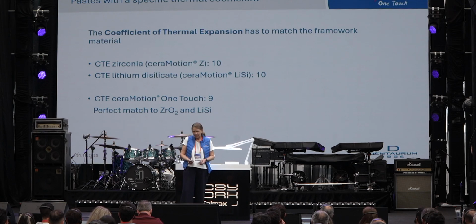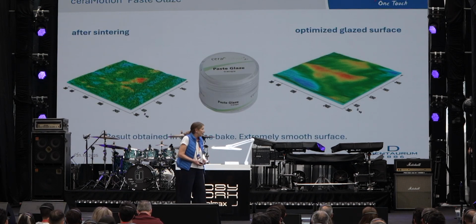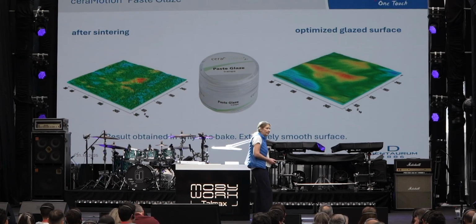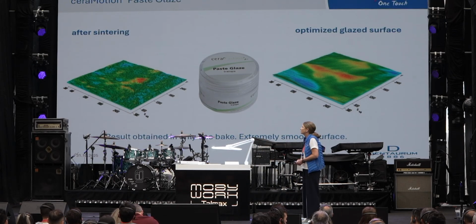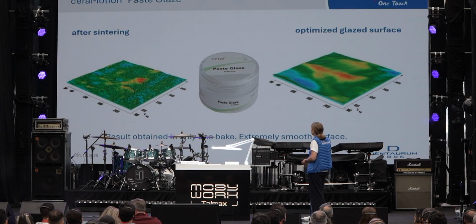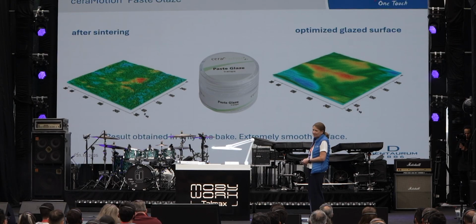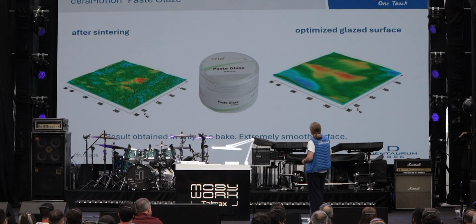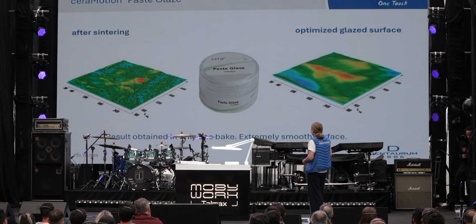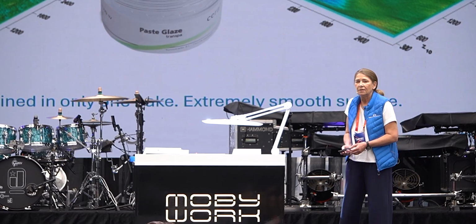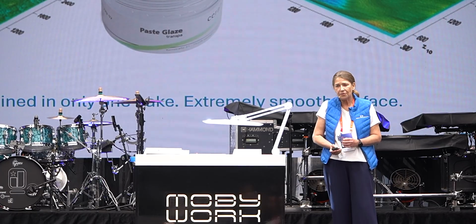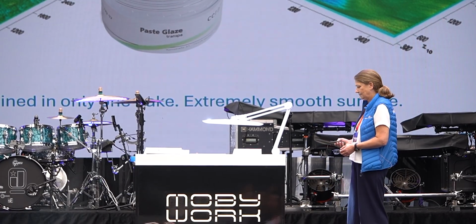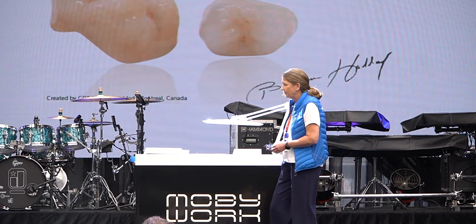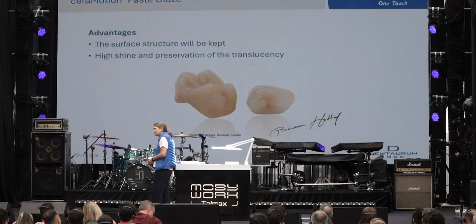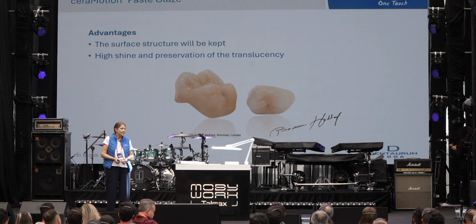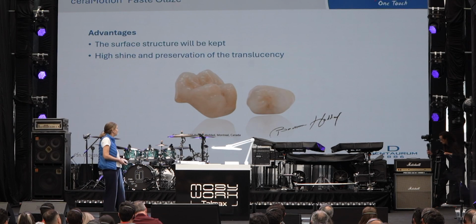Now, let's have a look at our paste glaze. The paste glaze is the mother of the whole system. On the left-hand side, you see a surface right after sintering, and on the right-hand side, you see the optimized glazed surface. You can achieve this in only one bake, with a very thin layer. What's the benefit of this? Your structures will be kept, and of course, the translucency of your monolithic crown will also be kept.